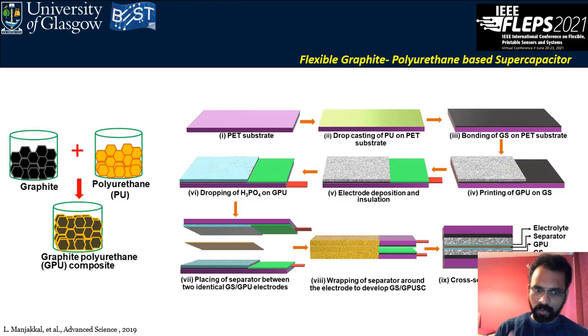As reported in this previous work, the fabrication here is almost similar, where we used PET or PVC as a substrate, and on top of the substrate a graphene sheet, a multi-layer graphene sheet, which is a commercial electrode.